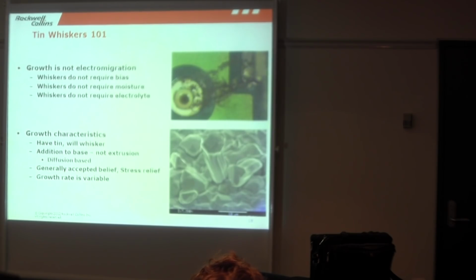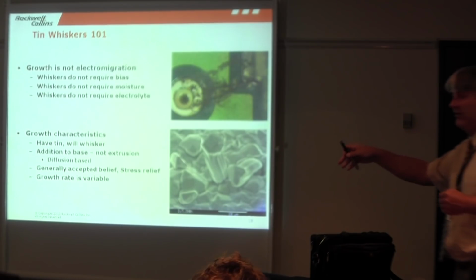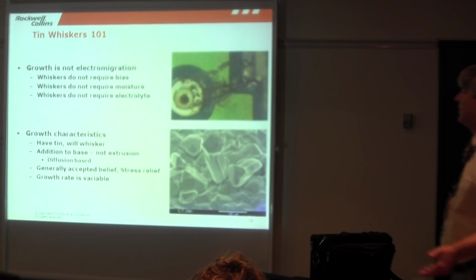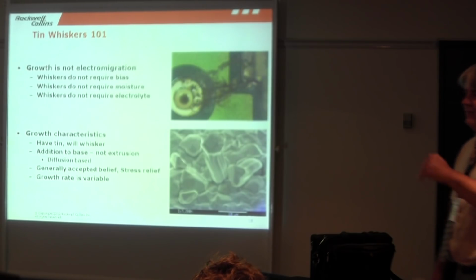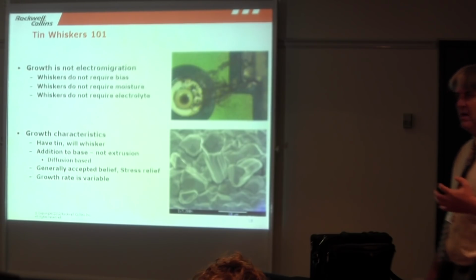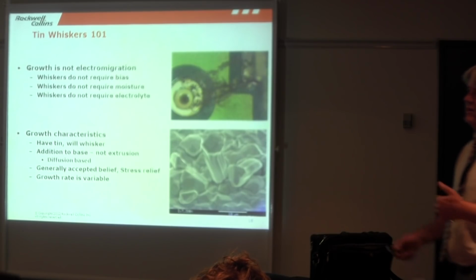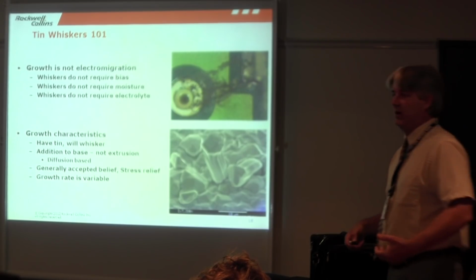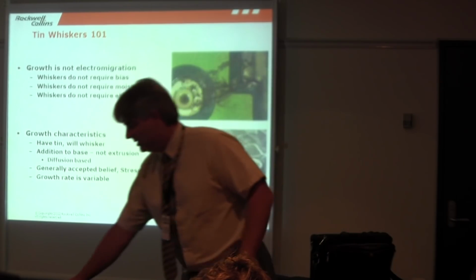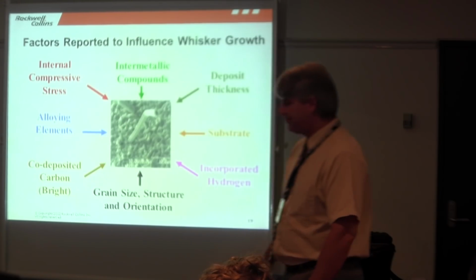It's just a common mechanism. The growth rate on these is pretty variable. You can see them grow like crazy, or sometimes they'll grow and stop. Sometimes they'll just grow and never grow again. Sometimes they'll grow, stop, and grow farther 5 years later. Again, that's part of the problem. As engineers, we don't have a nice prediction. There's no formula to say, okay, I know it's going to grow at this certain rate, therefore I can use that as part of my mitigation strategy. Just, it's not documented, it's not understood well enough.